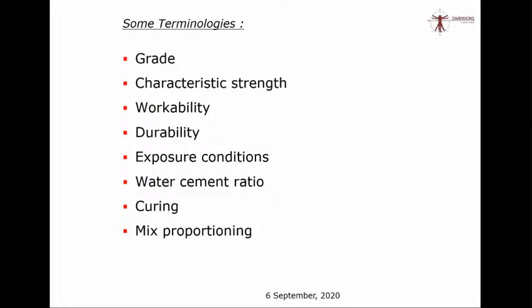Water cement ratio, we understood what is Abrams' law. One basic moral which we should never forget is higher water cement ratio means lower strength and lower durability. Curing is an important process in which you ensure that the water cement ratio which you have added during the preparation of concrete is very effective. Which means curing is not a process of adding more water. Curing is some technology. It need not even involve water. You can do curing without water also. So there are curing compounds, which is basically the protection of the water cement ratio, ensuring that the water cement ratio what you have added is fully utilized by the cement for its hydration. So that is the process of curing.